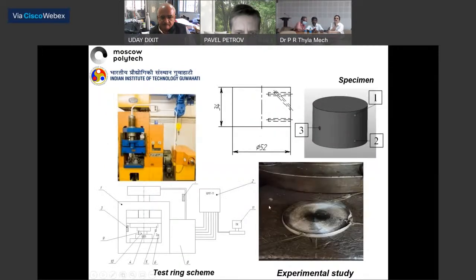Experimentally, we proved this increase in temperature, and for the experimental test within the collaborative project with the Indian Institute of Technology Guwahati, a special test ring was designed, which allows to control the temperature rise within the deformation zone online. So thermocouples are installed within the deformed material at several points, and during the deformation, the data is driven to the computer and then treated within a definite algorithm, and the value identifying the temperature rise is visualized on a special program.